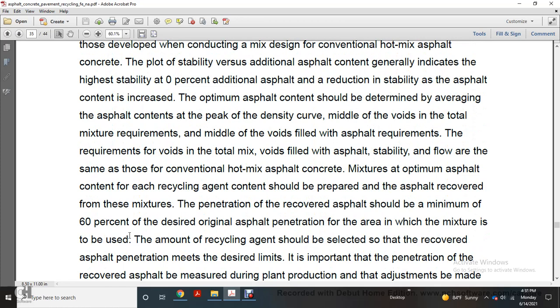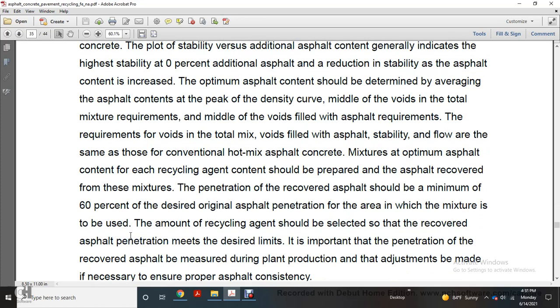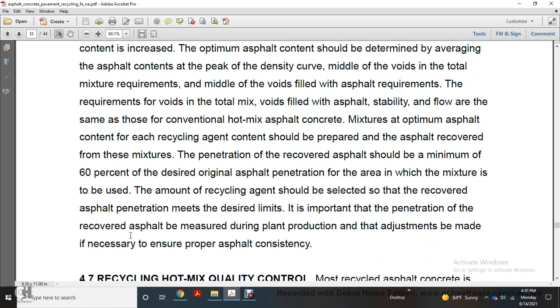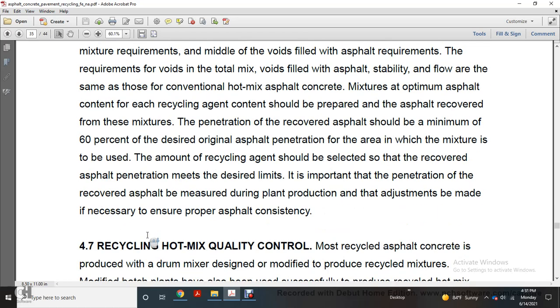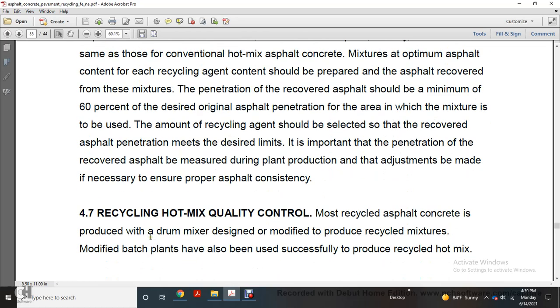The recovered asphalt should have a penetration of a minimum of 60% of the desired original asphalt penetration. The amount of recycling agent should be selected so that the recovered asphalt penetration meets the desired limit. It is important that the penetration of the recovered asphalt be measured during plant production, and adjustments made if necessary, to ensure proper asphalt consistency.